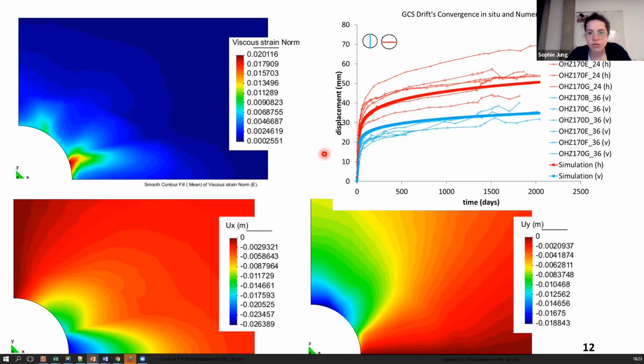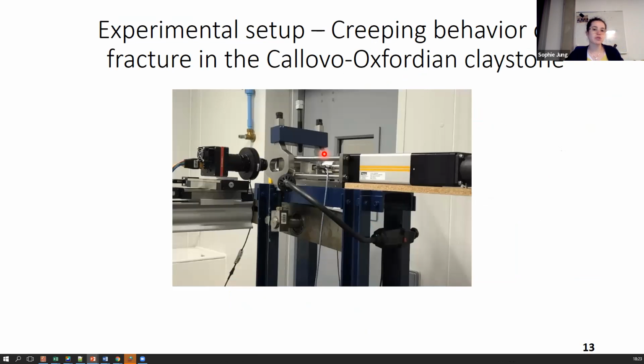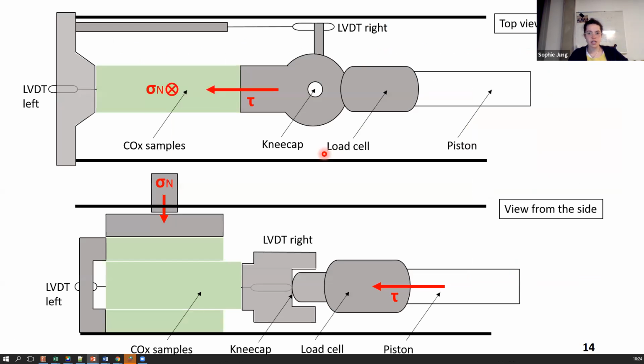So I'm going to present now the experimental setup, in order to study the creeping behavior of a fracture in the Callovo-Oxfordian claystone. The experimental setup is designed to investigate the viscous behavior of a fracture in the Cox claystone, which comes down to studying the slip of the interface between 2 blocks of the rock under constant shear stress. The blocks are also kept under constant normal stress. The setup is composed of a cylinder controlled by a LabView software that will apply the shear force, and an oedometric frame that you cannot see here, but that allows applying a constant and stable in time stress normal to the fracture.